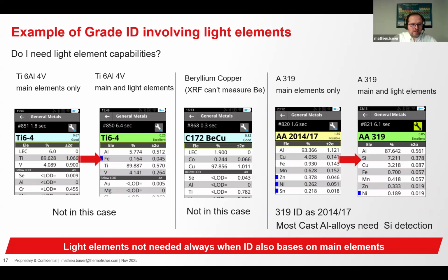Here are some examples of grade IDs involving light elements, and the question is, do I really need the light element capabilities to identify those grades? So a first example is a titanium 6-4 grade, which could be identified within 2 seconds without measuring the concentration of aluminum. There on the screen, the right grade alloy is identified within 1.8 seconds, and the nominal concentration of aluminum is also displayed as LEC, which stands for light element content. So we need then a bit longer time, about 6 seconds, to detect aluminum, also with a pretty high precision. So in this case, it's not a must to detect the light elements.